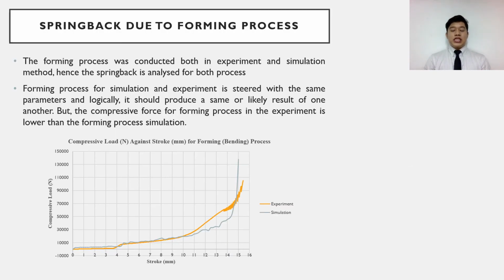The result and discussion is divided into two sections, which are the springback due to the forming process and the distortion due to the welding process. For the first section, the springback, the forming process was conducted in both experiment and simulation. The forming process simulation is set with the same parameters as the experiment, and logically it should produce the same or similar result, but the compressive force produced in the forming process in the experiment and simulation is quite different. For the experiment, the compressive force at 15 mm stroke is 105 kN, while the simulation is 140 kN.